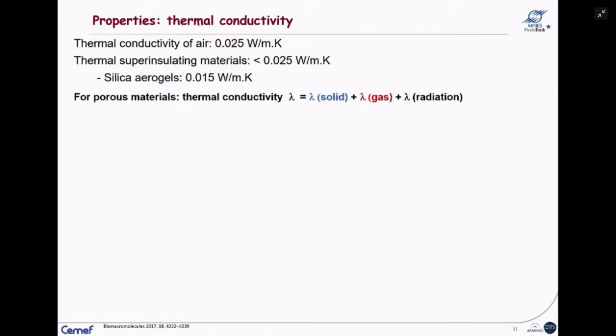And as I mentioned, the silica aerogels, it is a thermal superinsulating material. What it means is that the thermal conductivity of silica aerogels is lower than the conductivity of the air. So it is a bit magic that you have a matter that you hold in your hands, a porous material, which has a thermal conductivity lower than the surrounding air, with this material having air inside the pores. And this is due to physical effects.